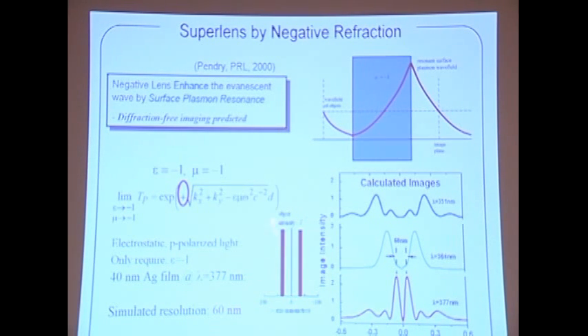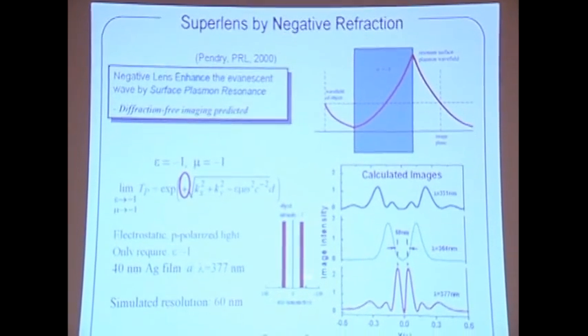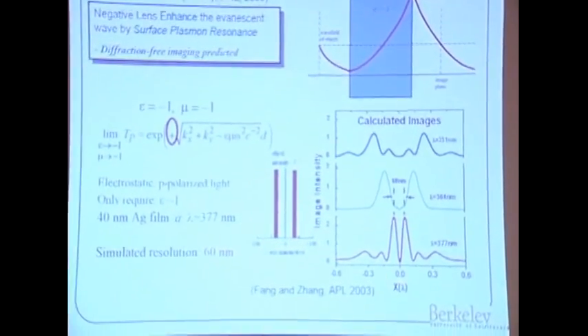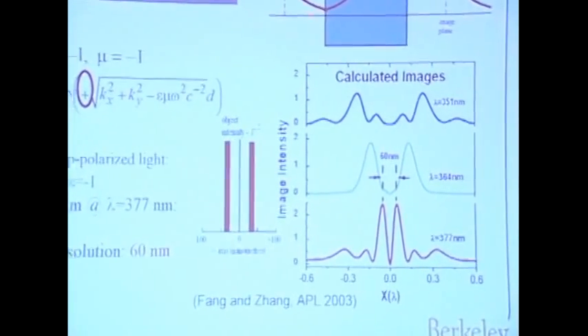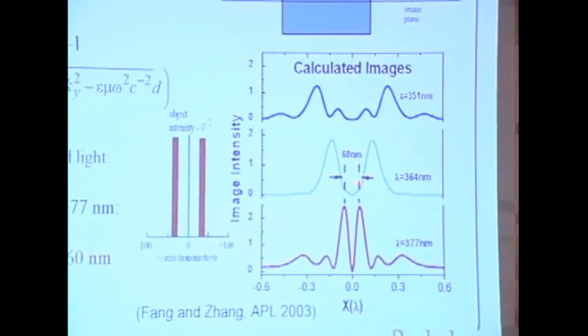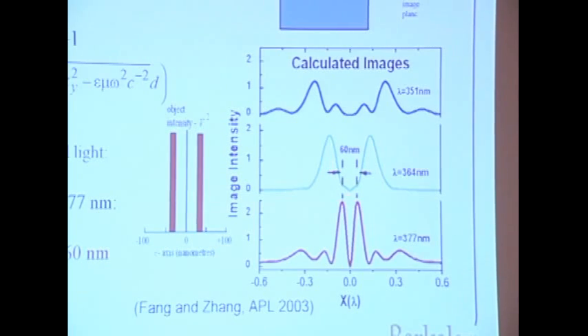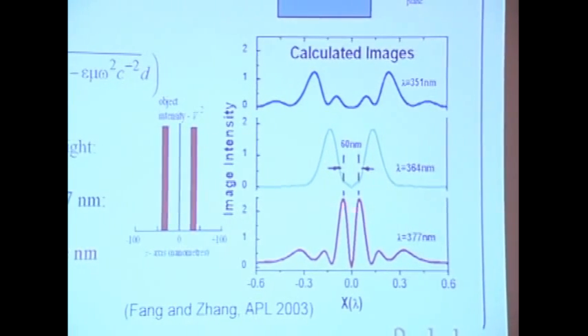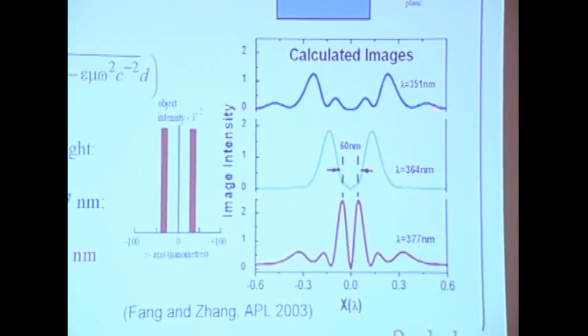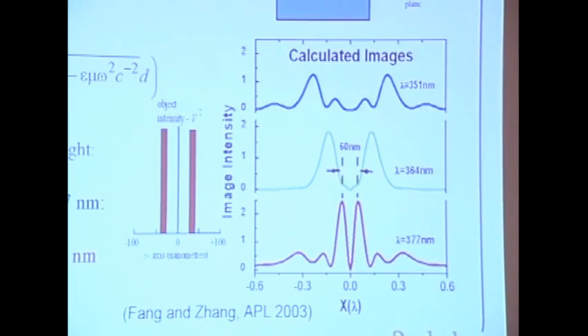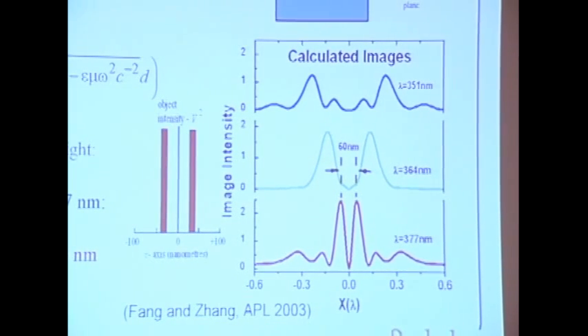So here is shown two nanowires, from our early calculation, that you can actually image separated by about 60 nanometers. You can image them with excitation of different surface oscillations. In this case, it can be a surface plasmon, okay? And not only can you have a reduction, but also an enlargement of the image. So you can do a little bit of both.